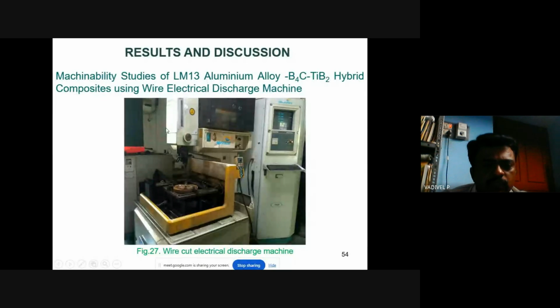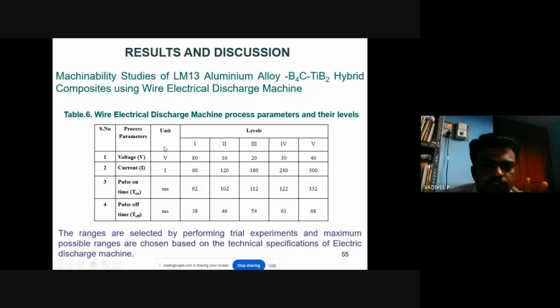And now we come to the machinability studies of this hybrid composite, aluminum alloy with titanium diboride and boron carbide, using the wire electrical discharge machine. This is the picture of the wire EDM, and here are the machining process parameters and their levels. The process parameters are voltage, current, pulse on time, and pulse off time, with their units, and we have chosen levels from 1 to 5. These ranges are selected by doing some trial experiments, and the maximum possible ranges are chosen based on the technical specifications of the electrical discharge machine. So with these, we have taken the parameters and their levels.